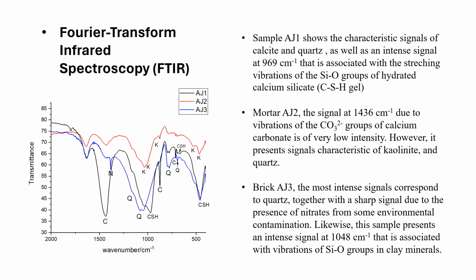In mortar AJ2, the signal at 1436 centimeters -1 is due to the vibration of the CO3 -2 groups. The calcium carbonate is of very low intensity. However, it presents signals characteristic of kaolinite and quartz.